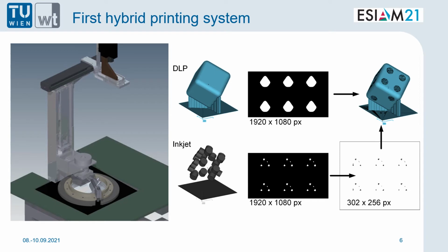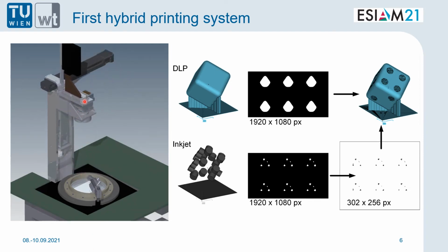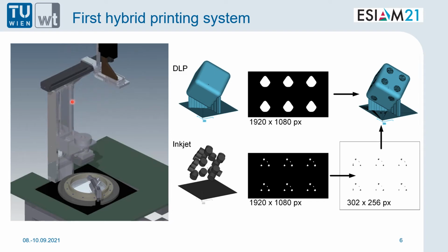This notion of selectively placed weak interfaces brought forth the idea to modify one of our existing DLP-based printing systems and add an inkjet printhead. Inkjet is not really famous for outstanding toughness, but it is able to precisely and selectively place tiny ink droplets of several picoliters on nearly any surface. After curing one layer, the printhead moves up, turns around, and the printhead jets tiny droplets on previously defined places. It is also absolutely necessary to have a clean and dry surface in order to be jetted upon. To combine those two systems, one CAD file is generated for each, and both systems have different resolutions and boundary conditions which have to be aligned.